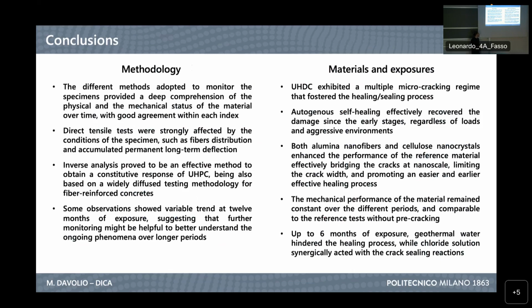And for our material and for the exposures we observed, of course, the self-healing capacity of the material was confirmed, and specifically the nano-additives fostered the healing and the mechanical performance of the material. While for the exposures, we observed a positive contribution from chlorides to seal the cracks due to the binding of chlorides inside the matrix, while for geothermal water, the sealing process was hindered in some cases.